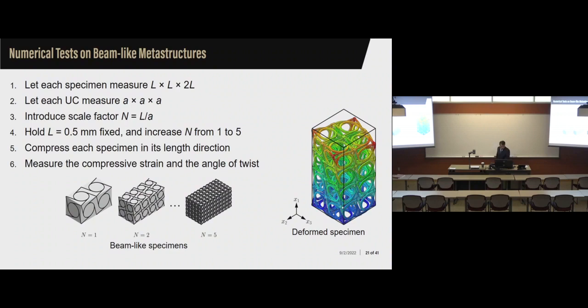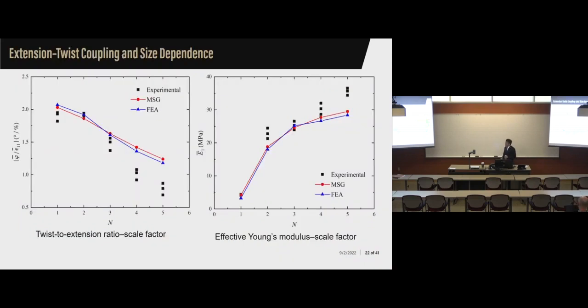In that paper, they did the test of the so-called size effect by increasing the number of N along the beam direction or the in-plane direction or three dimensions. They try to find out whether this so-called new property or new behavior will disappear or not. That's the FEA analysis they did. But for us, to predict the extension-twist behavior, we don't have to use so many unit cells. We only need to use 4 unit cells there, because that's our SG.